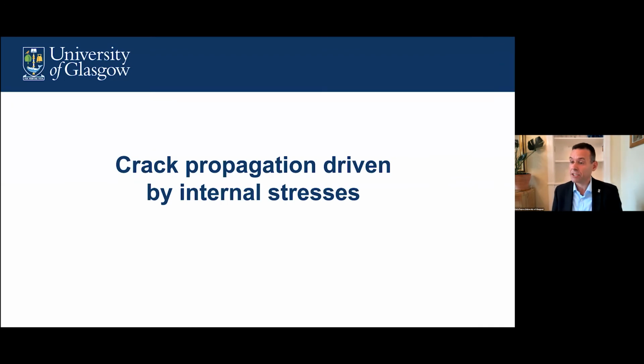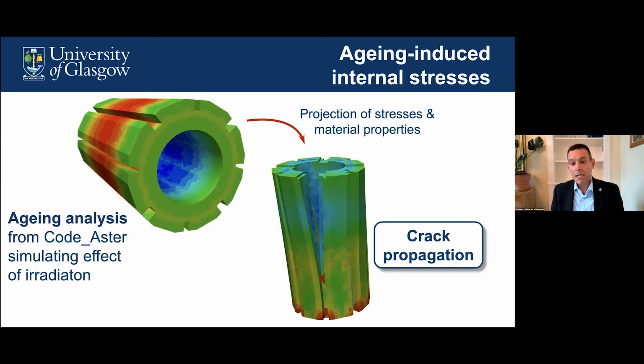But the real challenge has been in extending the formulation to drive the crack propagation by internal stresses. So what we've done is we have to first of all simulate the aging process, and so capture the effect of radiation on the development of internal stresses and material properties. And then we map those onto a finite element mesh of the brick that allows us to then do a crack propagation analysis.